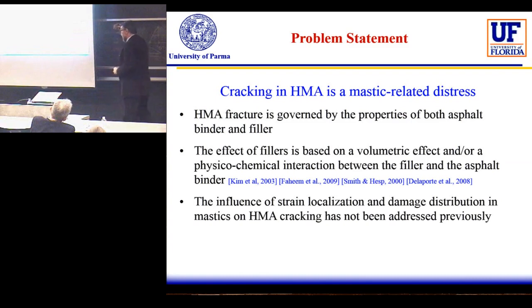So the problem statement in this part of the research was that cracking, together with other properties, is a mastic-related distress. So the change in the mastics, or the change in the filler, we call mastics the combination of filler and bitumen, is something that can strongly modify the properties of the material. In particular, we are looking at the fracture energy and the tensile limit. In the literature, it is clear from the work of several researchers that the effect of filler is based on a volumetric effect and a physico-chemical interaction between filler and the asphalt binder.